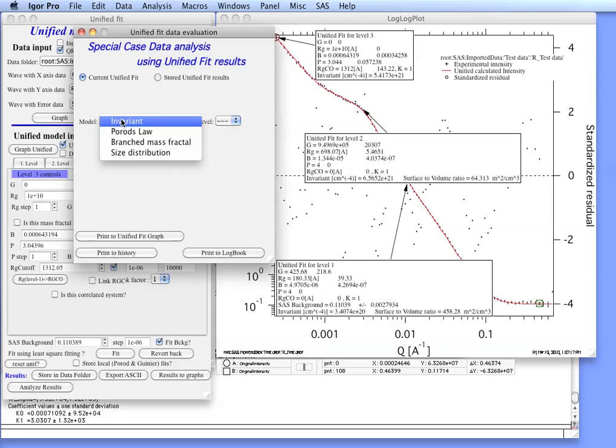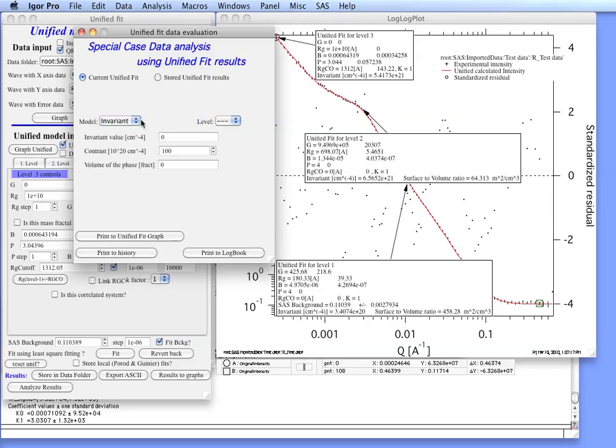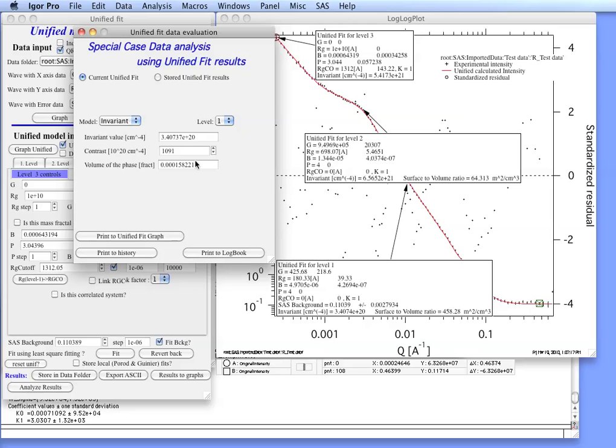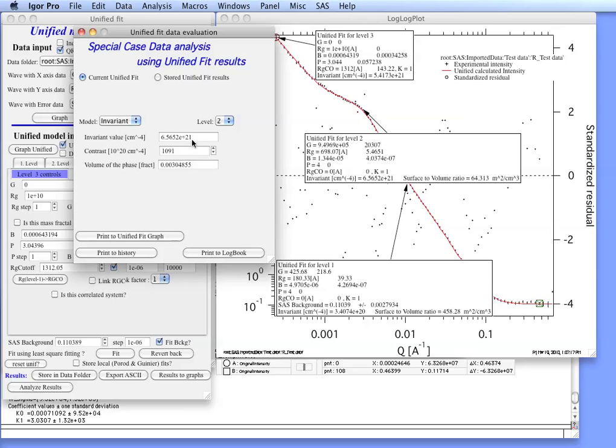There are currently four models available to you. You can analyze invariant of a level, let's say level 1. Now if you would know what the contrast of that specific phase is, let's say it's 10^21, and your data were absolutely calibrated, this is your invariant which is what you have in here. This is a contrast and this little tool just simply calculates the volume for you. Since our data were not absolutely calibrated, this may not be particularly useful in this case. But at least, for example, you can compare volumes. So in this case, if you look on this thing here, you will see that this is the volume from level 1 and that's the level 2 volume. And so you can see there is much more of the large particles than the small particles.